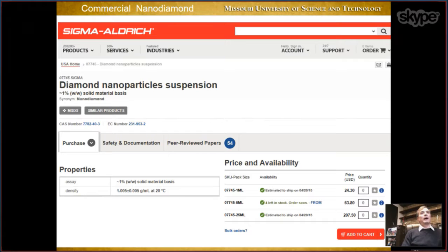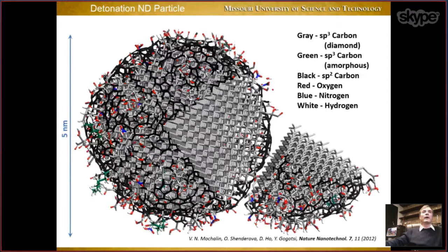to synthesize. Nanodiamond is a notable exception in this case, because nanodiamond produced by detonation is very cheap material, and it can be produced on a large scale, is available commercially, and you can even go to Sigma Aldrich website and buy it. Of course the price here is much more expensive compared to what you get if you just contact the manufacturer directly and buy this material from the manufacturer. But on average, the price of nanodiamond is comparable to the price of multi-wall carbon nanotubes, which is a few $100s per pound. So it's affordable material even for large-scale commercial applications.